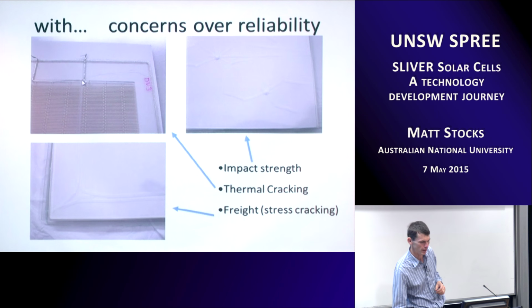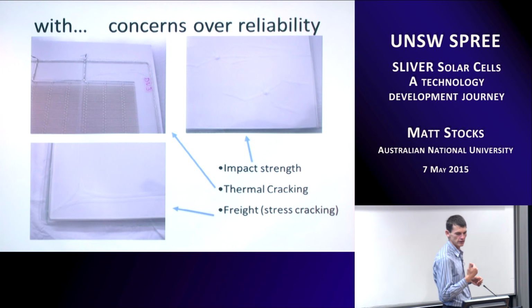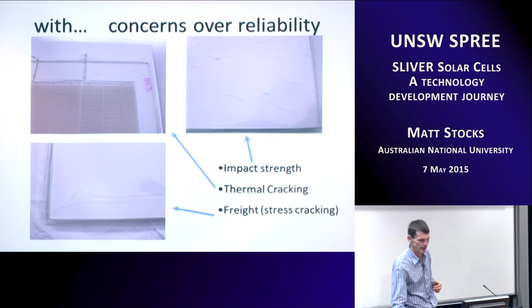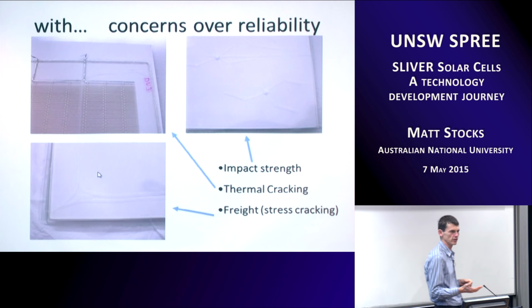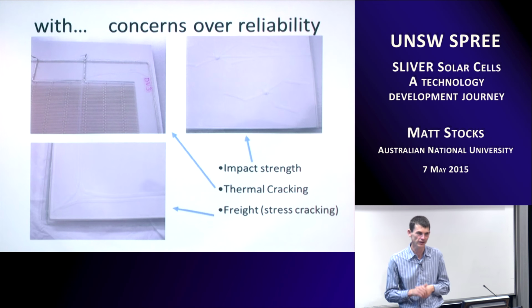We find that that front glass layer stresses too much. Hail test is a total failure. The glass separates and fails on that test. And even the handling, in terms of the glass suppliers shipping them to us, we're finding a lot of product was getting broken simply in the transport of those materials.